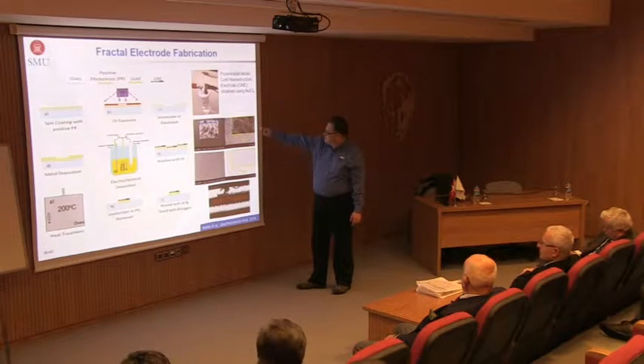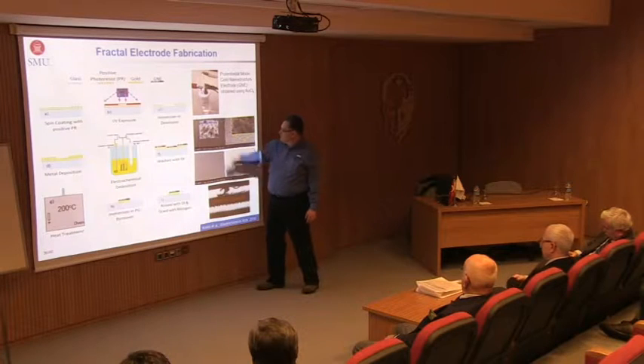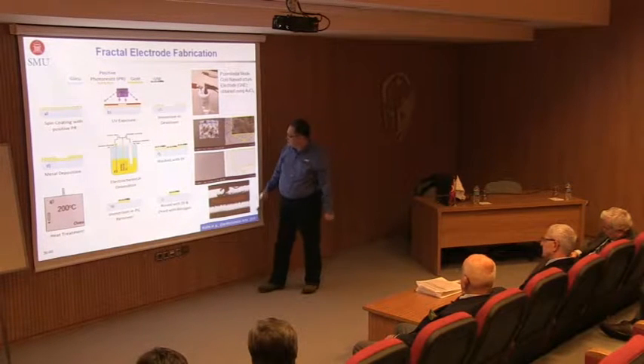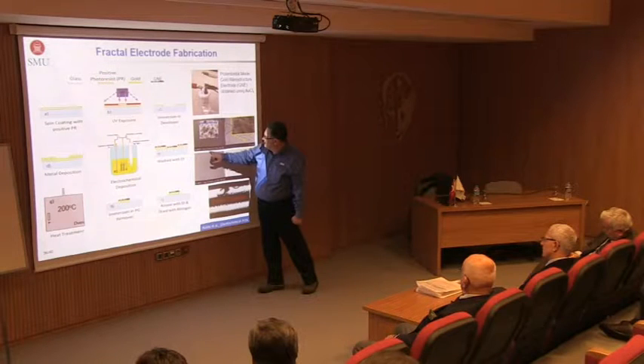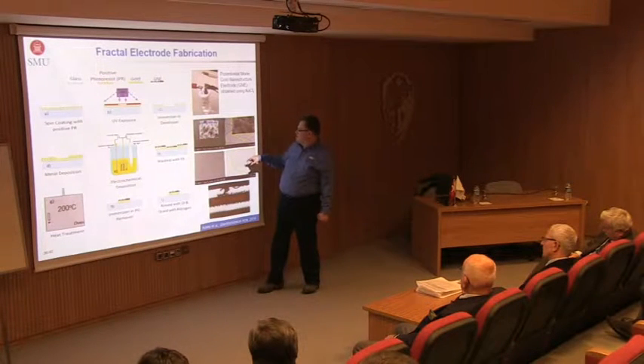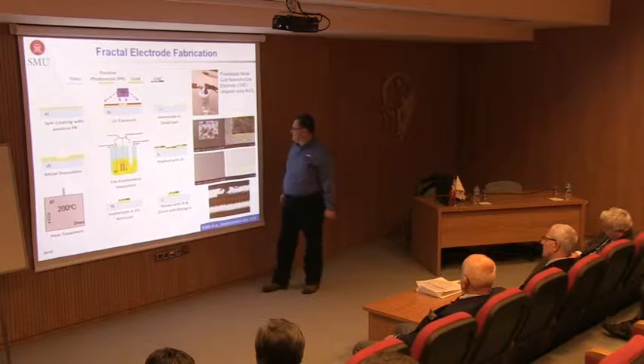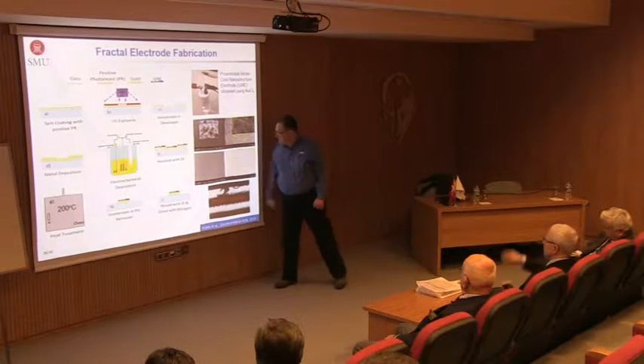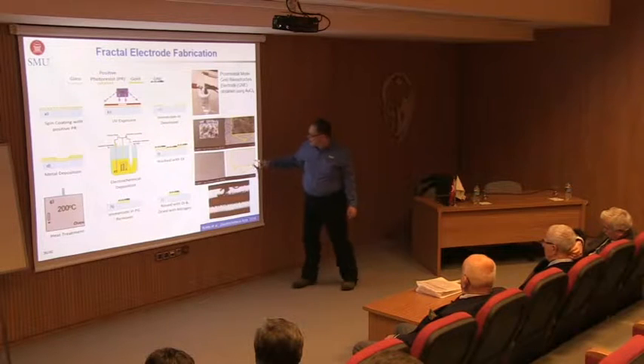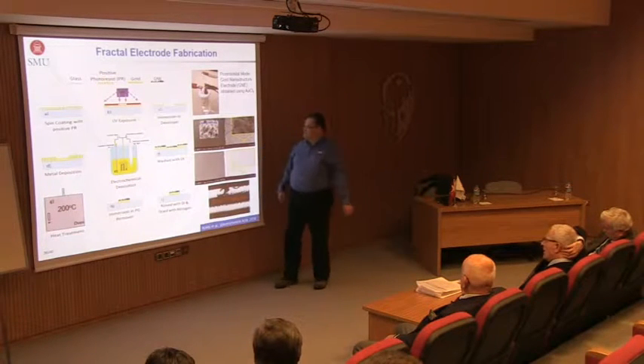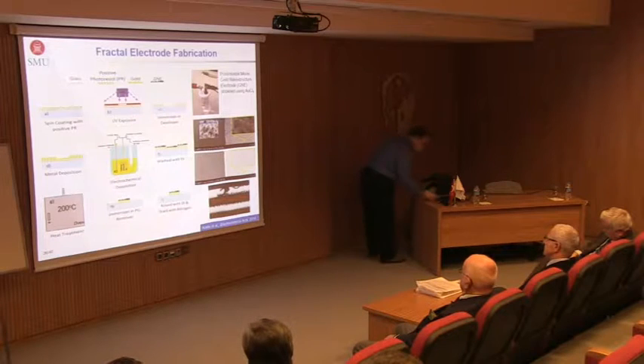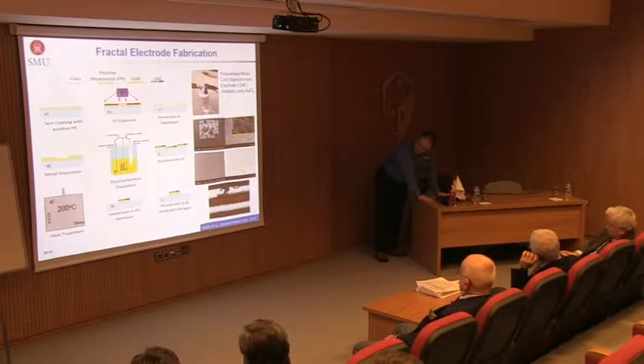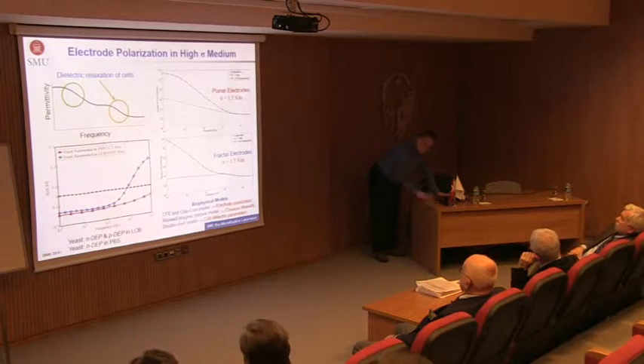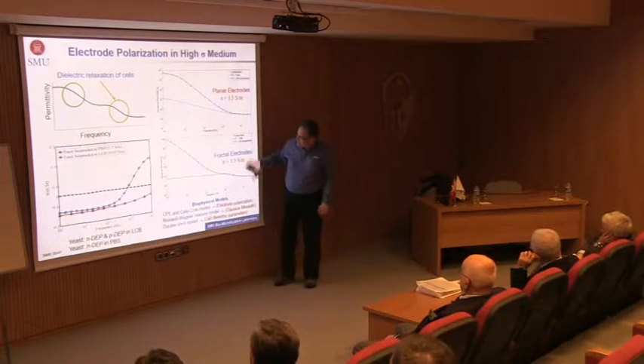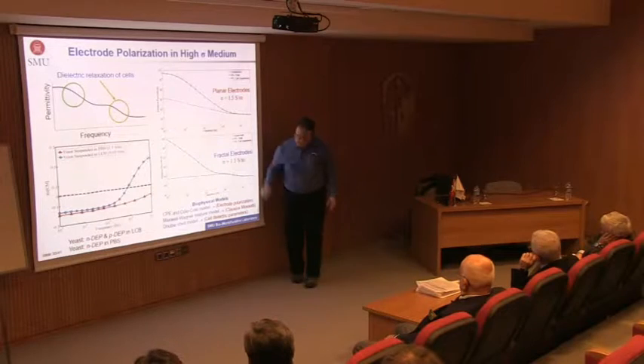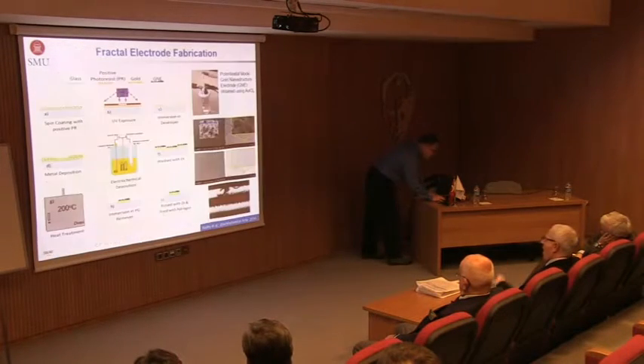So it works, and here's a picture of a fractal electrode with different magnifications. It's very hard to see how many times, but this is basically 75,000 times. And you can tell that there is a fractal similarity over here. And this is the smooth electrodes that we use. So indeed, it works extremely well that way, and we can actually measure, as I have shown up here. And now I have a way of measuring the electric properties of cells in high conductivity medium.